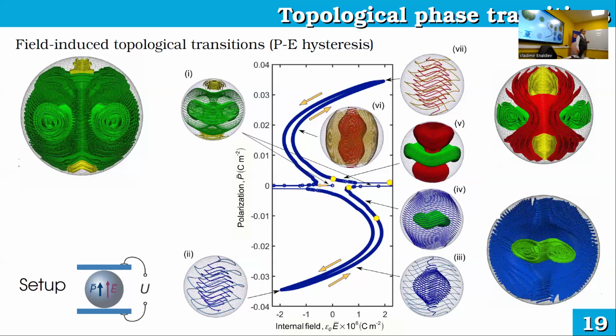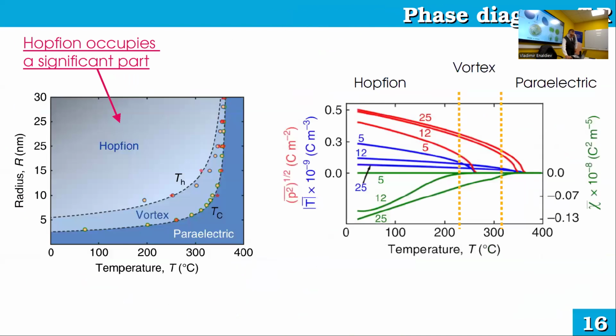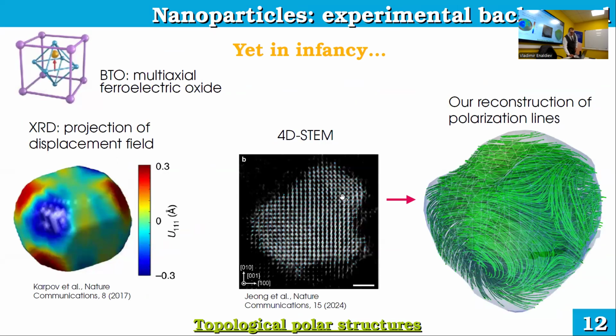But what is the criteria to detect it? Because hysteresis is not enough, right? First of all, you can utilize, for example, chirality. You can measure it by light, and if you see some signs of chirality, then it's definitely not vortex. Most likely, it's Hopfion. Of course, I showed you this very nice experiment with STEM on small nanoparticles, and these people did polarization mapping over the whole volume of the nanoparticle. But they reconstructed it not very properly. We did the reconstruction of lines, and actually it has signs of Hopfion. But it's not a true Hopfion because it lies on some grids that attract some charges. If you somehow can lift this particle, you will get Hopfion.